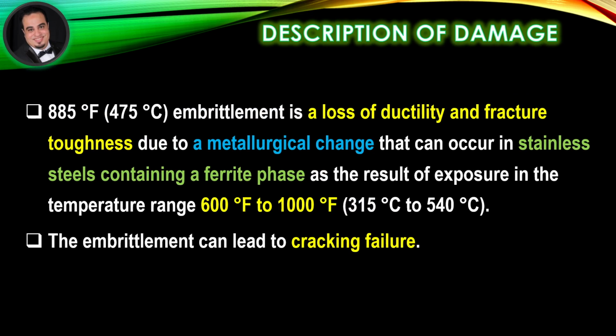885 degrees Fahrenheit embrittlement is a loss of ductility and fracture toughness due to a metallurgical change that can occur in stainless steels containing a ferrite phase, as the result of exposure in the temperature range 600 degrees Fahrenheit to 1000 degrees Fahrenheit. The embrittlement can lead to cracking failure.